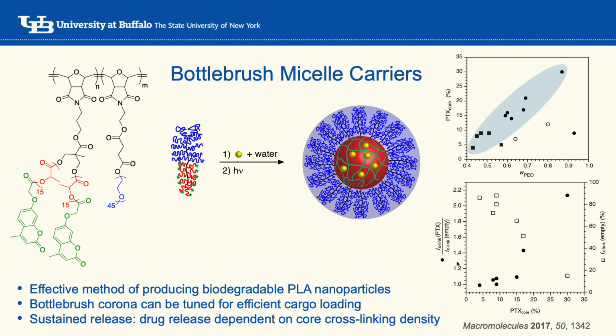And it increases because when you make this big, you create packing frustrations, and more space inside the core where the hydrophobic drug can go. So at the maximum, you can keep increasing. We can load up to 30%. So 1/3 of the core is composed of some hydrophobic cargo. And if you keep increasing further, it just drops because at that point, it doesn't form an efficient micelle anymore. The hydrophilic head is so big that it can't form a micelle.